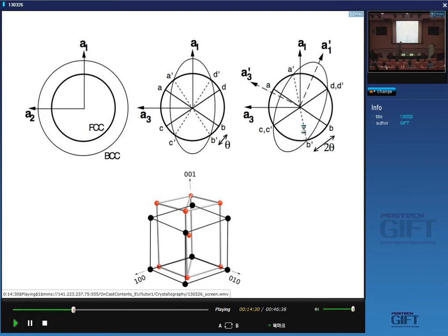But they are not coherent because the vector after deformation is rotated, right? So they are not matching perfectly because you've got a rotation. Yes, I can create an interface by taking a single crystal and rotating one half with respect to the other. That doesn't give me coherency, right? So these lines are not going to give us coherent lines. Although they are not distorted, they are rotated.